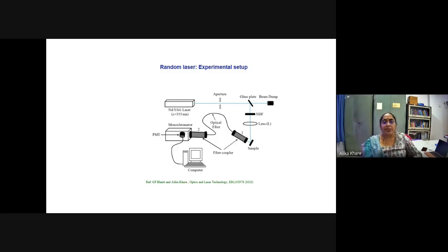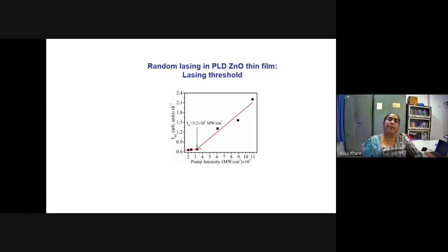Here is the curve which tells us that if, beyond a certain level, there is suddenly a very large increase in the radiation output, that shows laser action is taking place. So at this point, this is probably the threshold. Here I have plotted pump intensity as a function of laser output. At this point is the threshold, and beyond that, there is a sudden growth of the radiation.